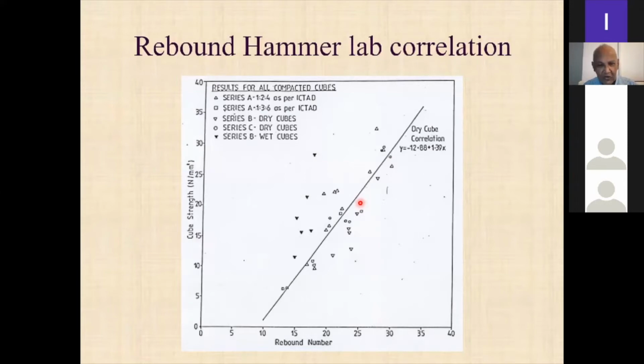But the other thing that I want to show here is that we had some cubes that were wet and some cubes that were dry. That is in order to get a bit of a spread of strengths also. Now, this correlation line is drawn only between rebound number and cube strength for the dry cubes, right? If you take the wet cubes, they have a range of strengths, but a very small range in rebound number, and the rebound number is fairly low also. Which means that strength has no effect on the rebound number.